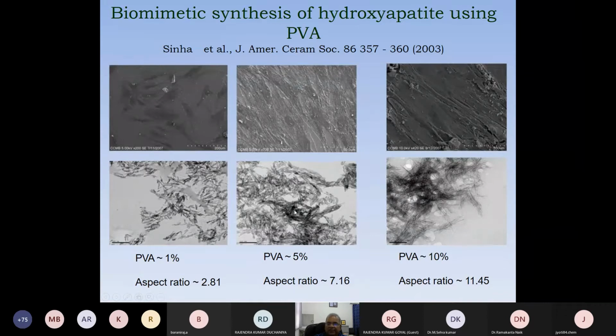Once we gave this sample to CCMB, Hyderabad, they have shown with the help of stem cells that an increase in the aspect ratio of the hydroxyapatite nanoparticles gives an order of magnitude higher adhesion of the stem cells on the inorganic nanoparticles, so they can help in the bone healing process. And this process, though I am showing here the microstructure, we developed on the semi-industrial or industrial scale. But hydroxyapatite is a biocompatible material. It does not instruct the body to heal. Once the body starts healing itself, it supports that healing process.